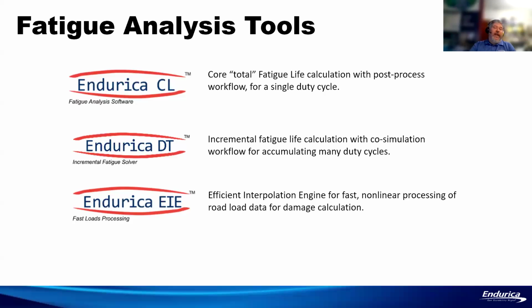And so you can see this maps onto the first two categories, infinite life or safe life analysis. Endurica DT is our incremental solver. With Endurica DT, you can specify block cycle schedules. You can do co-simulation. It's not necessarily purely post-process only. With Endurica DT, you can couple the Endurica solver with your finite element solver. For example, if you have cyclic softening, you can update the stiffness with cycles, if you have a stiffness loss type of failure mode.